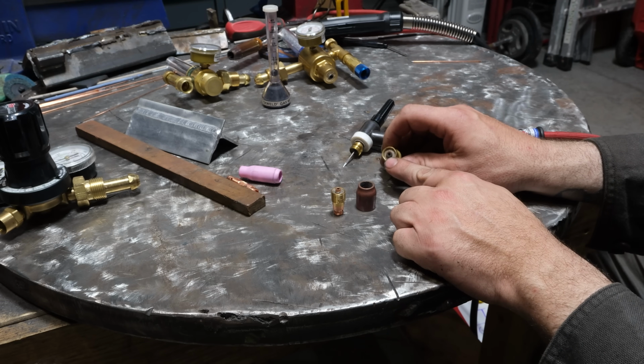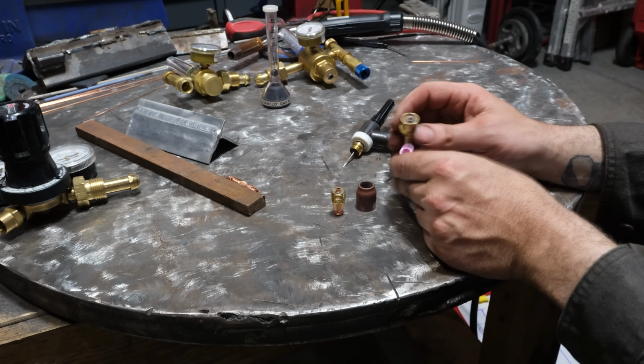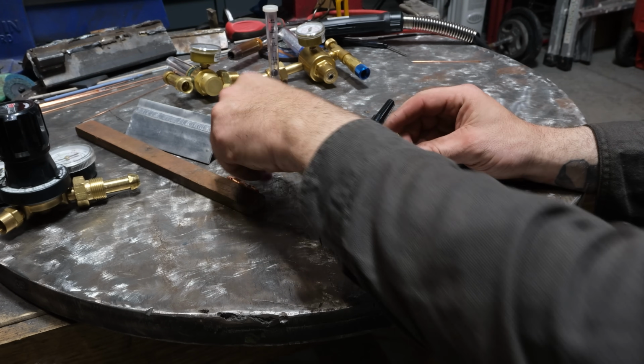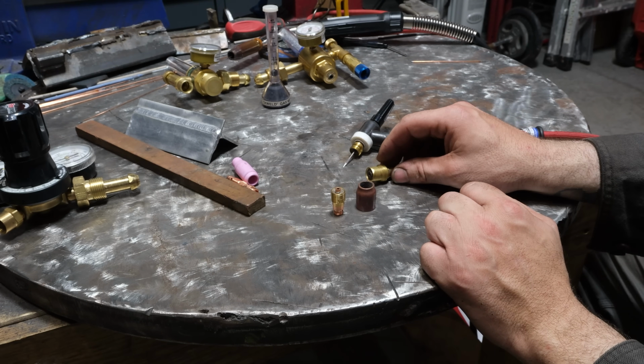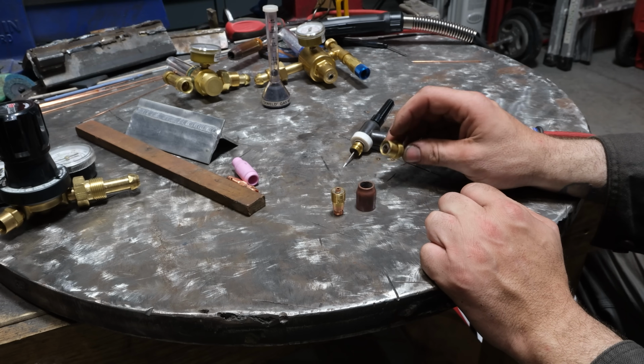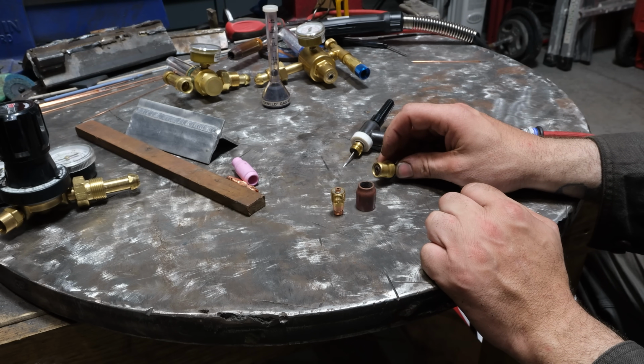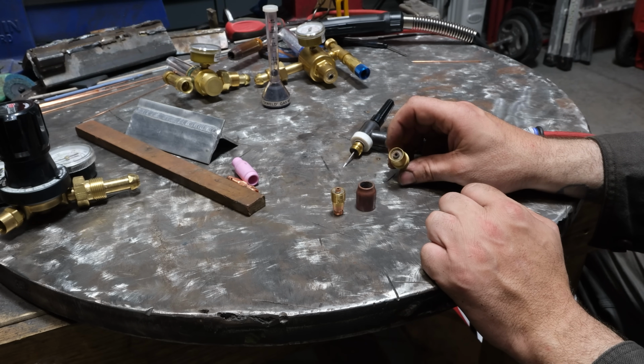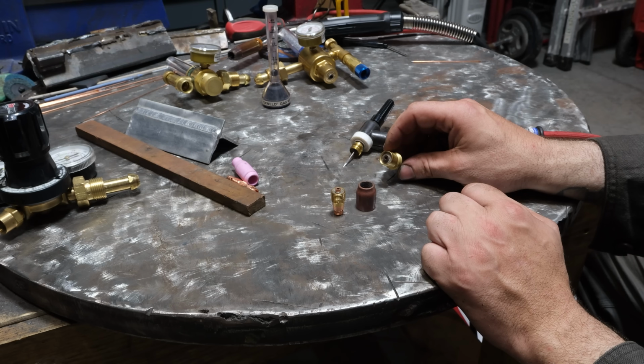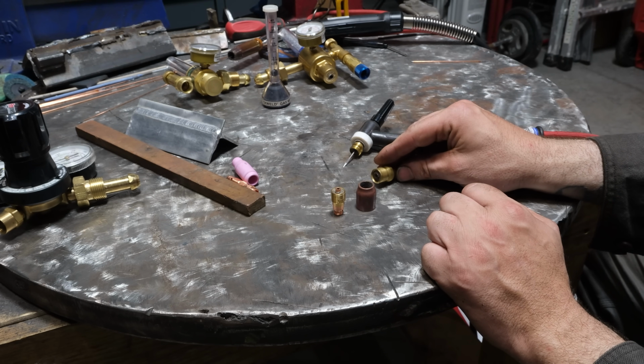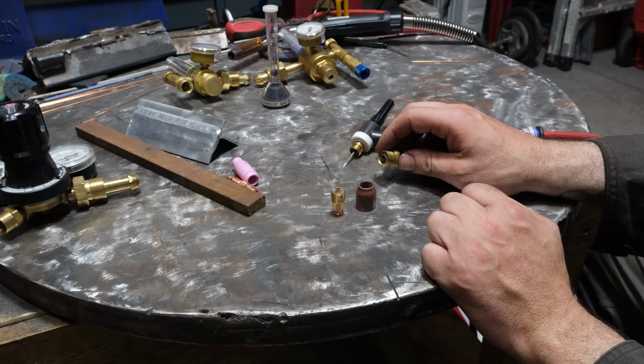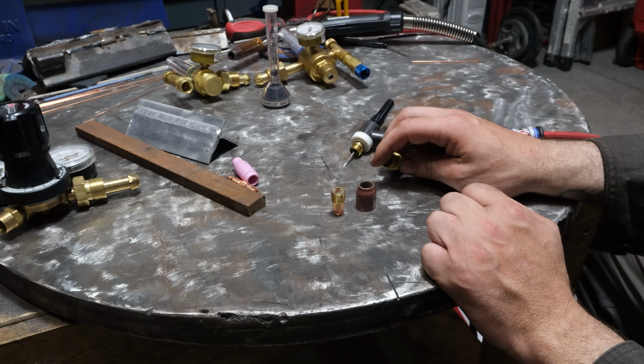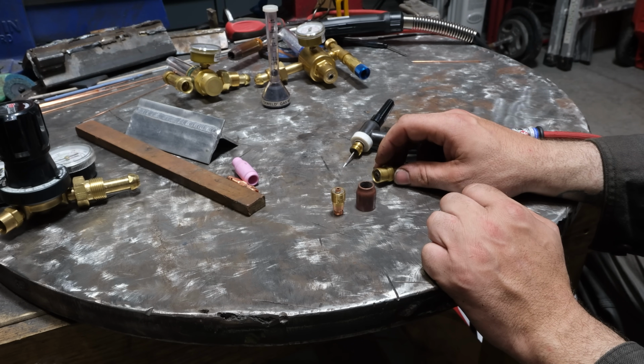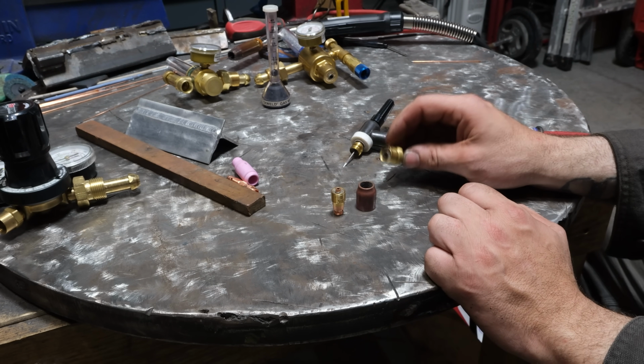And even though this is a bigger lens than this collet body, the gas shielding is better because of the laminar flow, or the lack of turbulence, works so much better, and since argon is heavier than air, it sinks. And on most joints you can run, in my experience, somewhere between 10 and 14 cubic feet an hour up to about 160, 180 amps with one of these, versus if you're using a collet body, you're going to get poor shielding with that at 15, 18. Even 20 sometimes. So get yourself a gas lens, 100%.